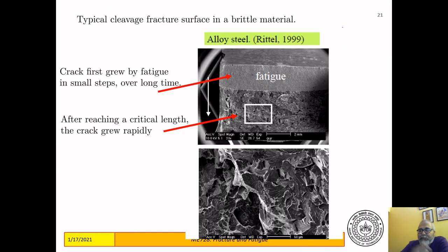This is a typical brittle fracture in an alloy steel. In fractography, you are again looking at the broken surface from the top. So what you see here is a clean surface. This is the part where it's a clean surface, and you can barely see, but they're present, the marks of striation around this. So these are the steps that the fatigue crack has taken, but these are not very tall, so you can barely see them at this resolution. It looks like a clean surface, but here, this is the crack front.